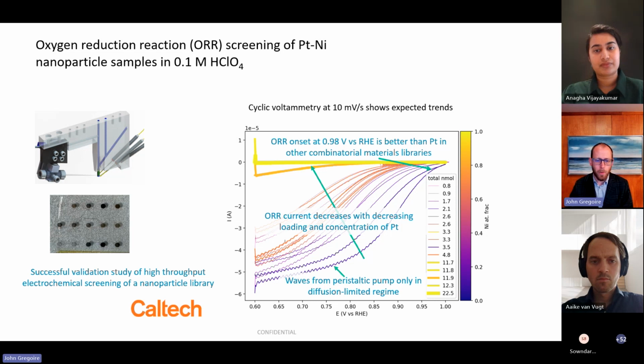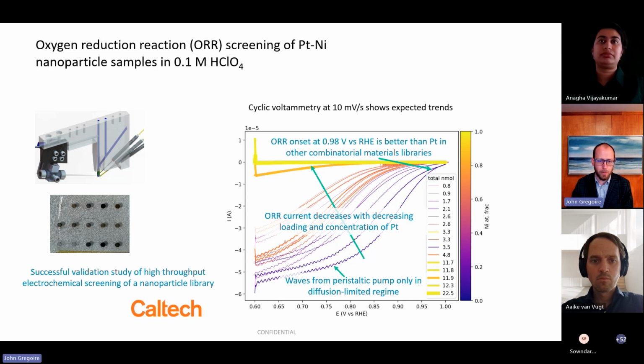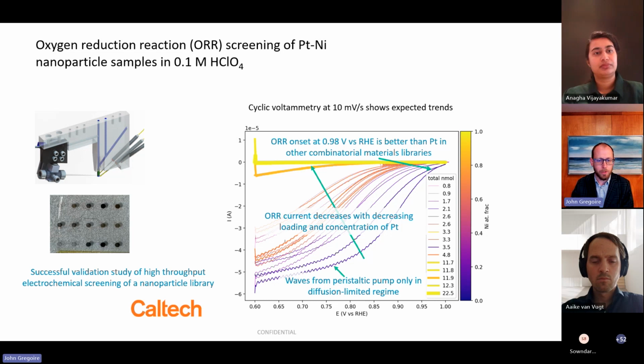waves. Those are waves from the peristaltic pump, right? That's the frequency of the peristaltic pump you're seeing, which changes the effective flow rate near the surface. And these waves are apparent when we're in a diffusion limited regime, particularly because this is oxygen reduction and we have a limited supply of O2 to be reduced. But when you're in a catalyst kinetic limited regime, you don't see those oscillations because the local delivery of O2 is not limiting.